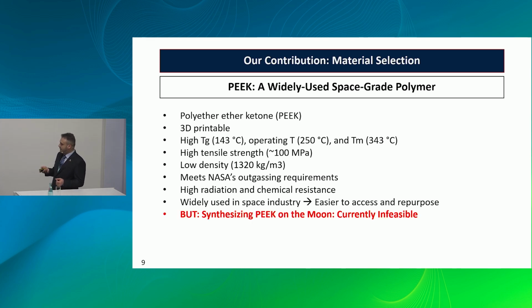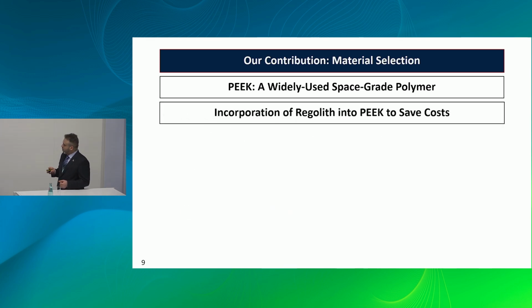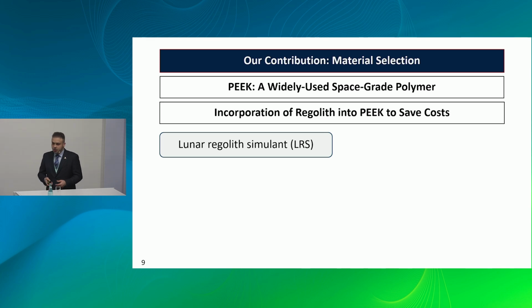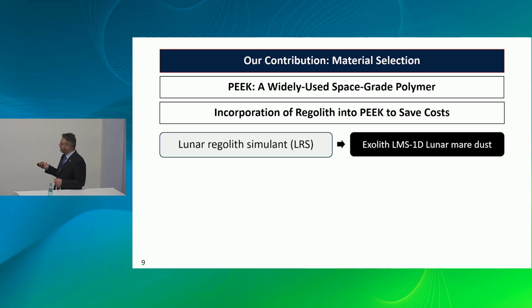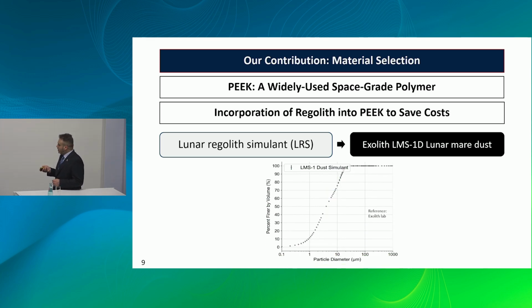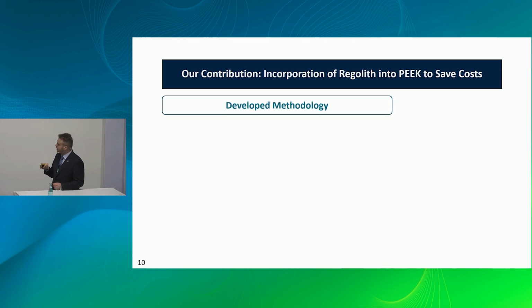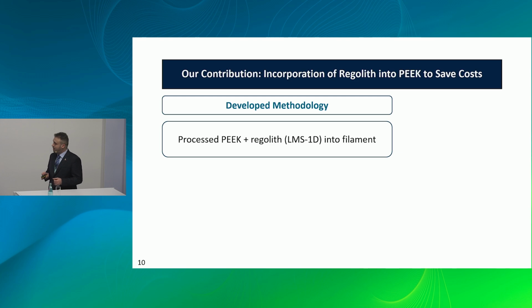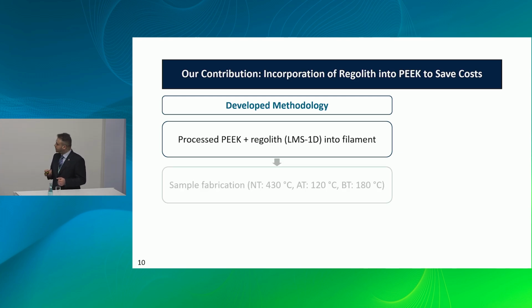But synthesizing PEEK in the lunar environment is currently infeasible because there are no big resources of carbon on the lunar environment. So we can address that by incorporating regolith into PEEK as a filler to save costs. We don't have access to big volumes of regolith delivered from the Moon, so some simulants have been developed. We selected Exolith Labs LMS-1D Lunar Mare dust because it has finer particles compared to other simulants. The developed methodology includes processing PEEK and regolith into filament using a twin screw extruder, and then using a high temperature printer for printing the fabrication.